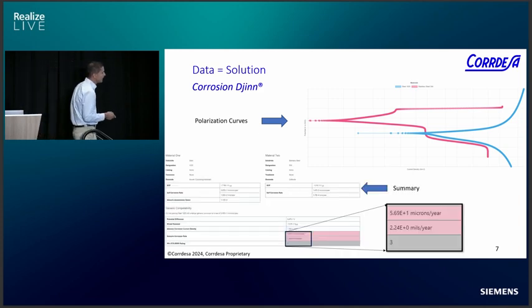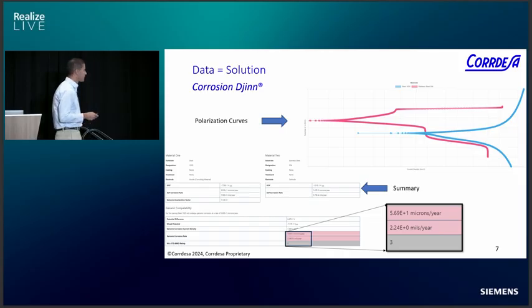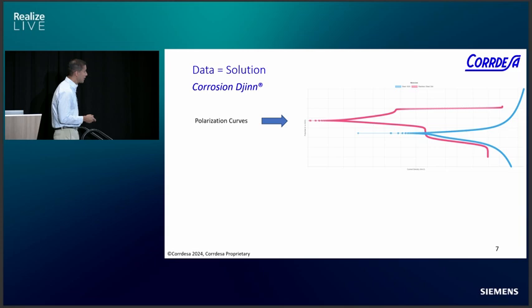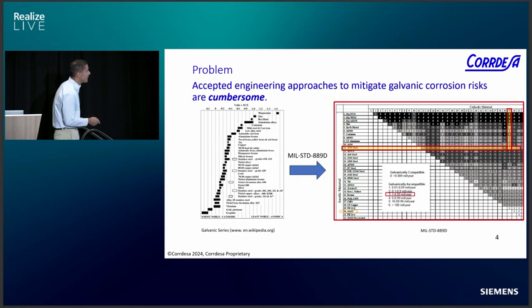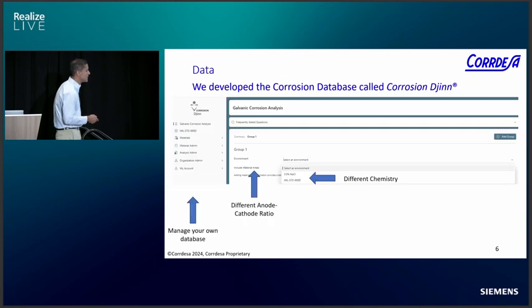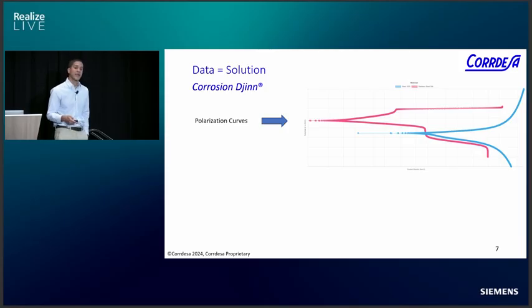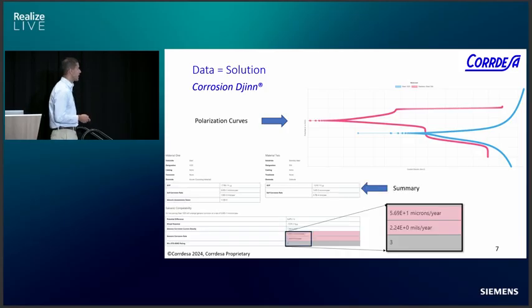So from Corrosion Djinn, once we run this, which takes a few seconds, it's actually really fast, we have information that is important for our electrochemical team. We have OCP, we have self-corrosion rate, we have all that information. But more importantly, we see that we get the same risk rating, the MIL standard rating, excuse me. In this case, it's number 3, and if I quickly go back, you can see that that was exactly the same number we have here. We use the same procedure in the back end called mixed potential. That's what we use.